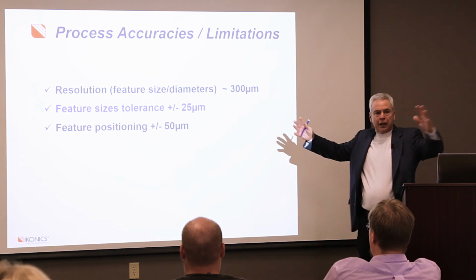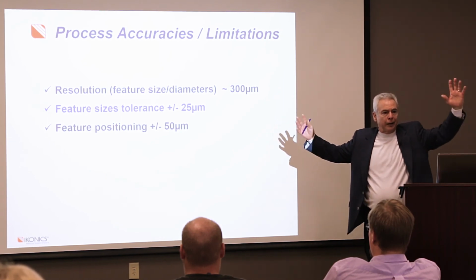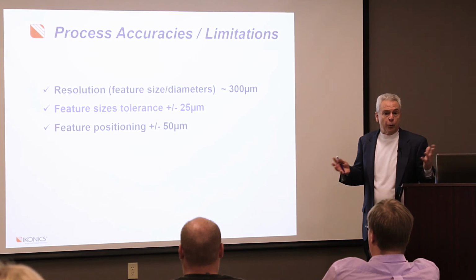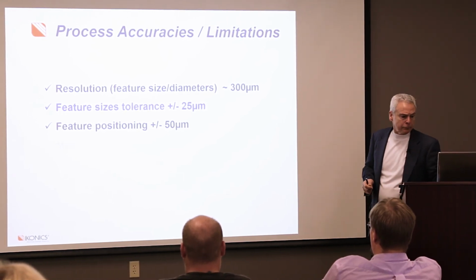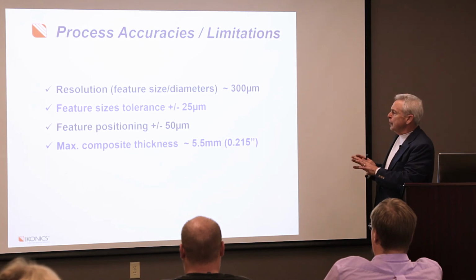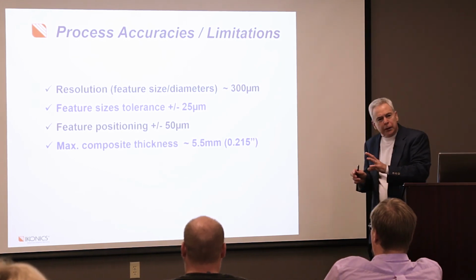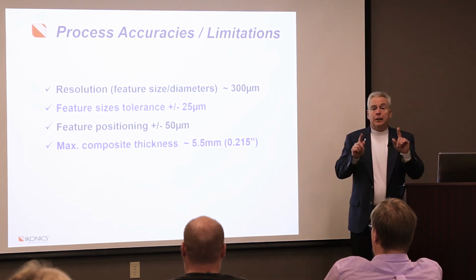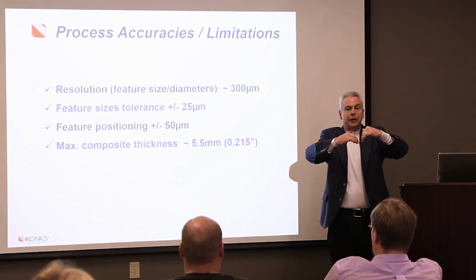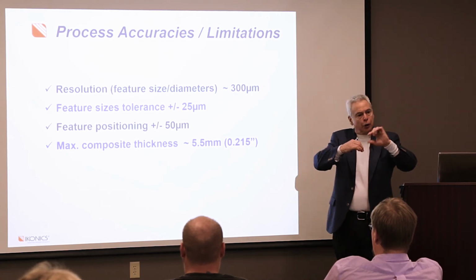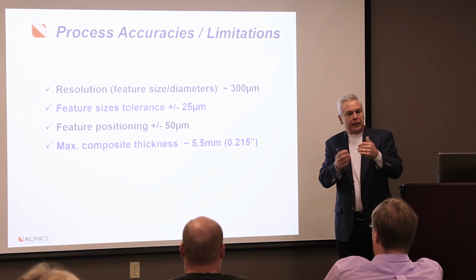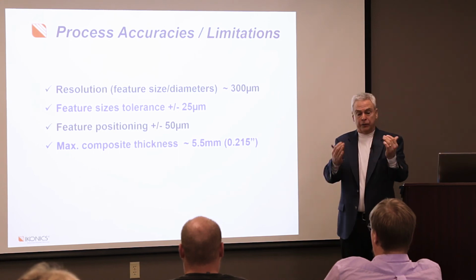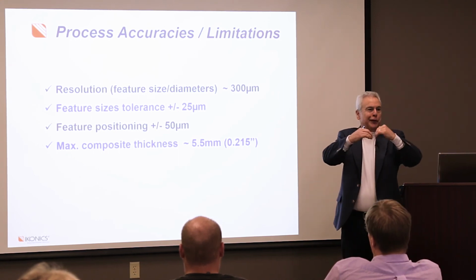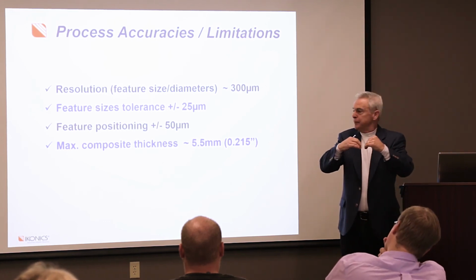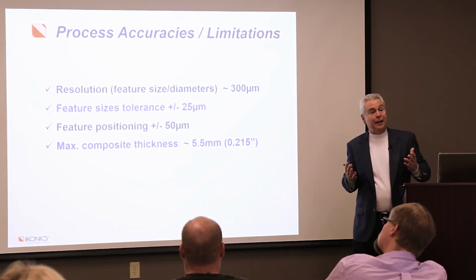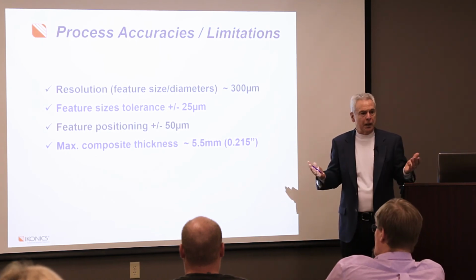Positioning of the features. You've got to remember these are huge panels, liners, and you can position all the features on that within plus or minus 50 microns. The maximum composite thickness is a little under 1/4 inch. And why is that? Remember what I said before, as you're blasting down, you start to lose energy. So you can only go so far. A lot of this is related also to the hole size, because the smaller the hole, the thinner that piece is going to have to be. So there is a thickness limitation, but again, for most of the composites used in the aerospace industry, not an issue.